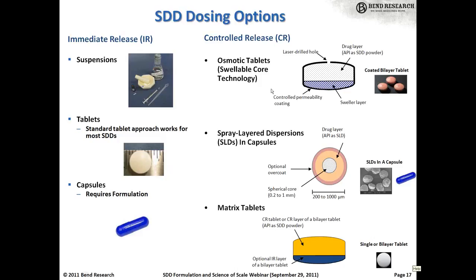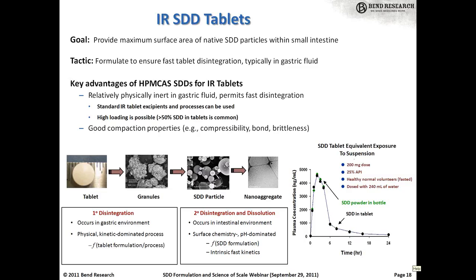SDDs can be placed into a number of controlled release presentations, including a swellable core or an osmotic type of tablet, as well as a spray layer dispersion. So with respect to immediate release dosage forms, again, the standard methodology that we use is an immediate release tablet. And the idea here is typically to recover the performance of the native SDD and basically match what you have with the suspension.